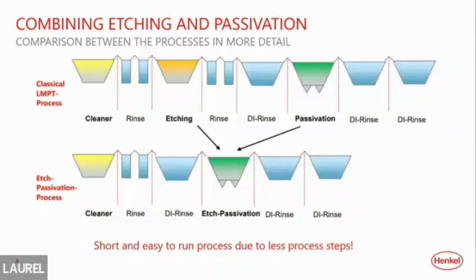So these battery trays were having problems with losing seal. And you don't want your battery tray to lose seal. You don't want contaminants, water, and all that other nasty stuff in your battery tray. So we worked with them and created this process. And the nice thing is we were able to shrink down the process, so we have a smaller footprint. We've actually reduced two stages, or two tanks at least, so you have less manpower and less water treatment.